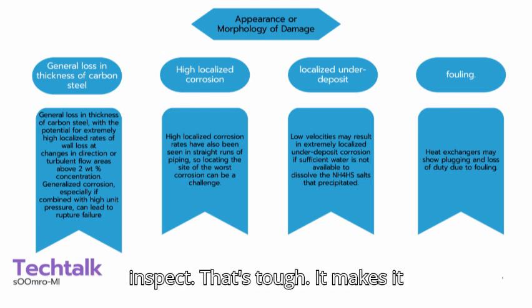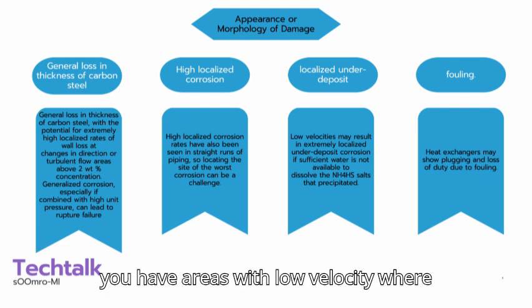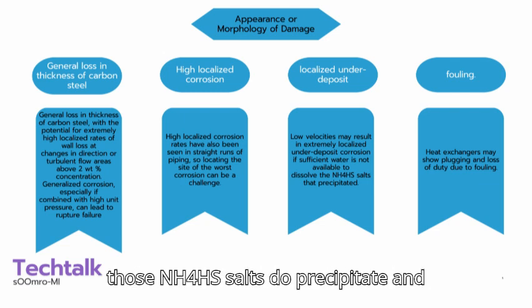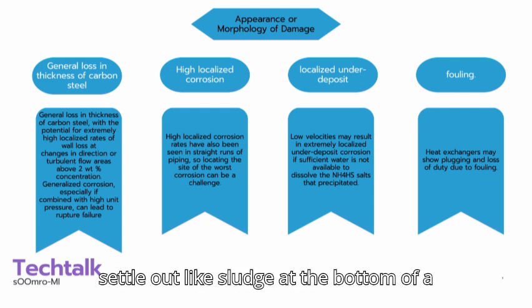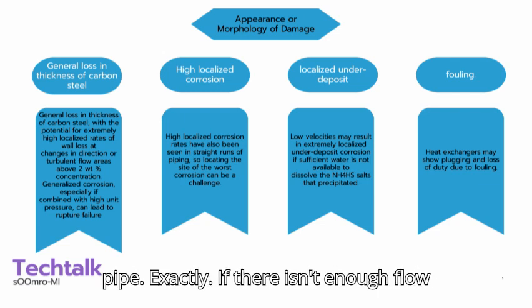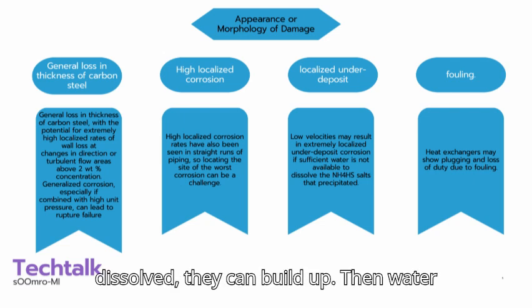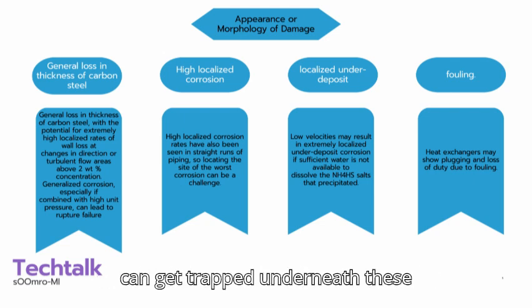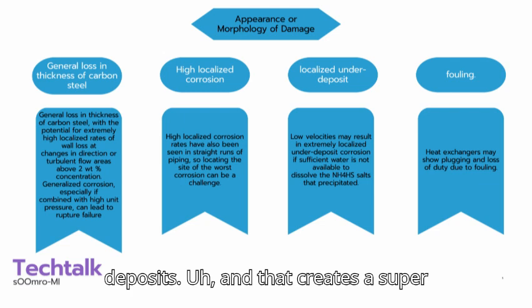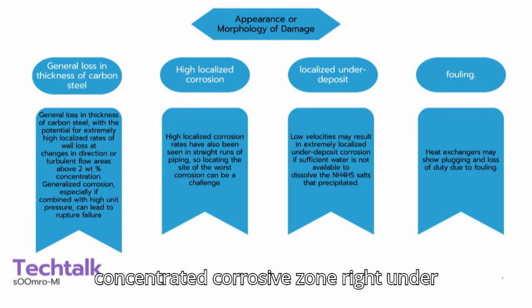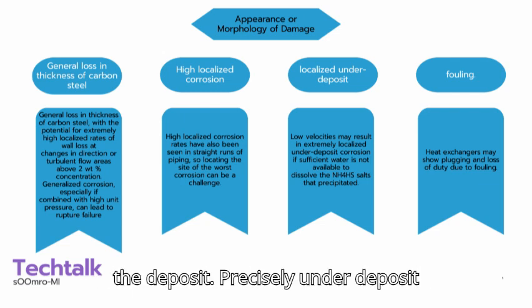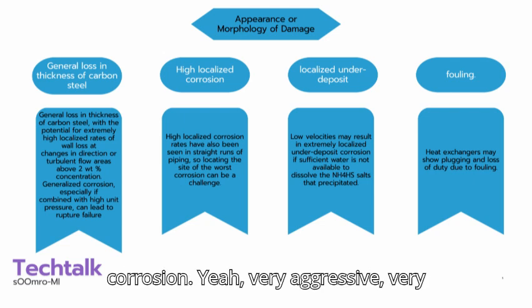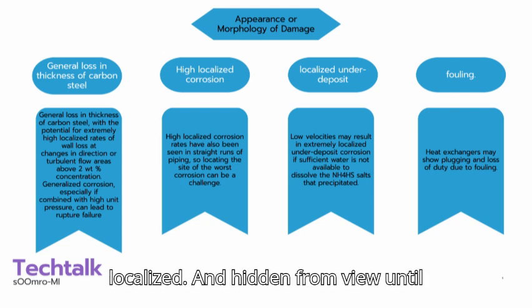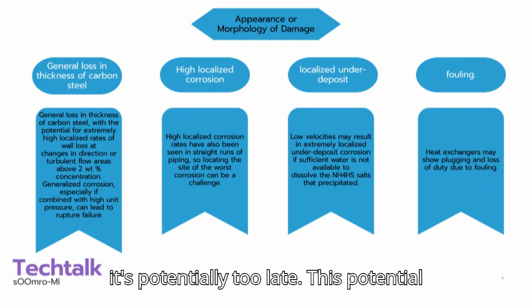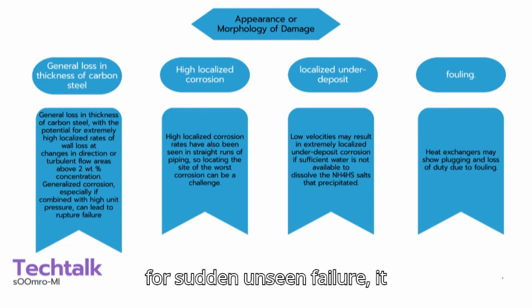That's tough. It makes it incredibly difficult. And add to that, if you have areas with low velocity where those NH4HS salts do precipitate and settle out. Like sludge at the bottom of a pipe? Exactly. If there isn't enough flow or enough water wash to keep them dissolved, they can build up. Then water can get trapped underneath these deposits. And that creates a super concentrated corrosive zone right under the deposit. Precisely. Under deposit corrosion. Very aggressive, very localized, and hidden from view until it's potentially too late. This potential for sudden, unseen failure.